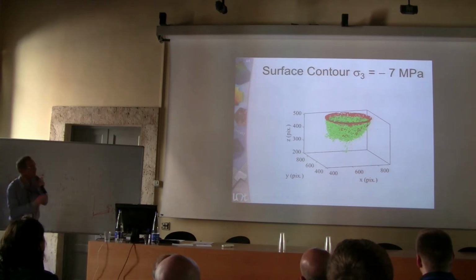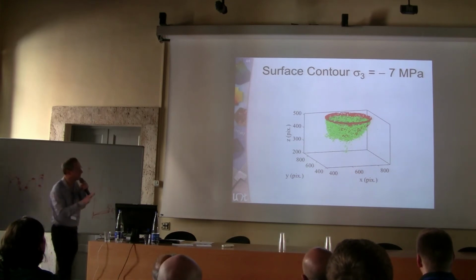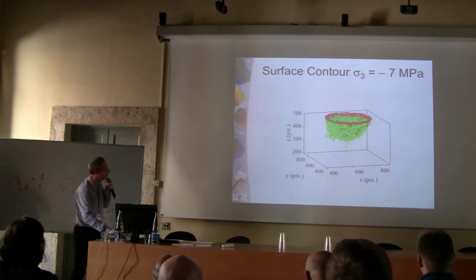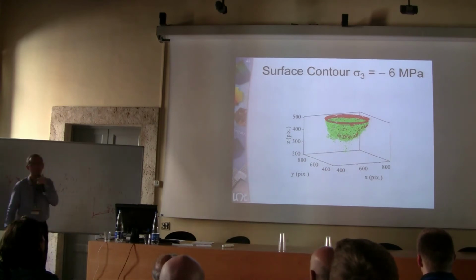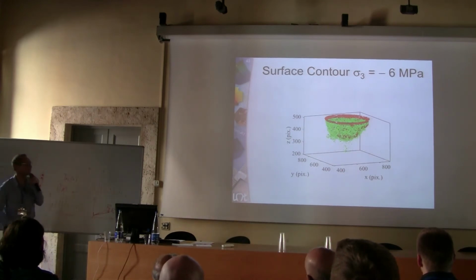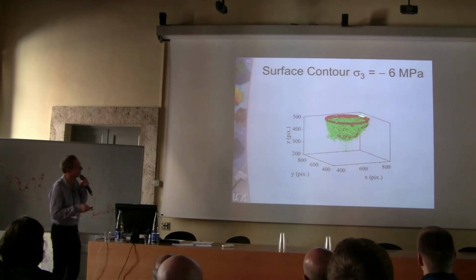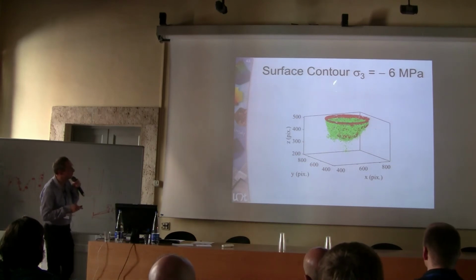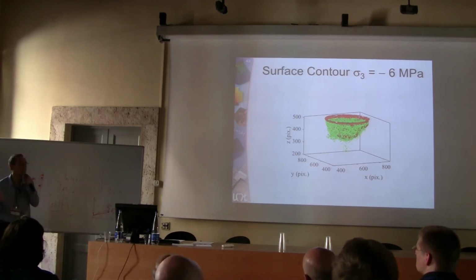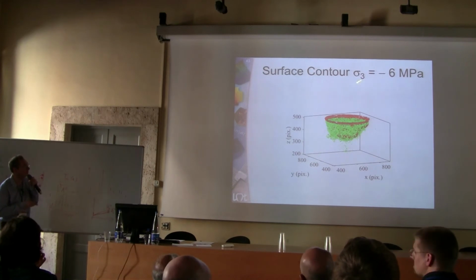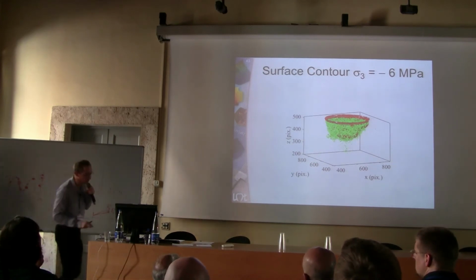So basically in this type of setting, it turns out that the best agreement was given by minus 6 megapascal, which means that you have a way of not only proposing a criterion but also validating it with experiments.